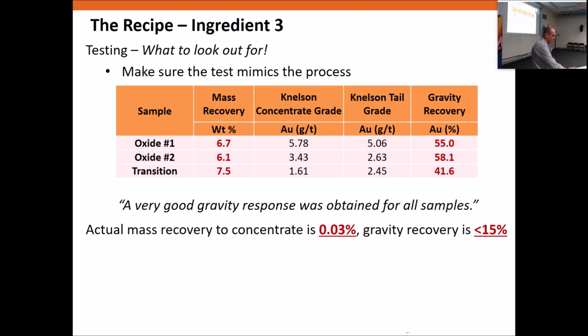I've got a couple of horror stories from labs, and probably the worst one, not this one up here, but the worst test and results interpretation we've seen from a lab was where they took the whole test feed sample and mixed it with mercury, and then took the residue of that and then did their standard flotation tests. And the gold that ended up in the amalgam was stated in the laboratory final report right up front in the summary section as being the gravity recoverable gold. And a plant worth 7 figures was actually designed and built with the expectation that they're going to get 50 or 60% of the gold in the gravity circuit.